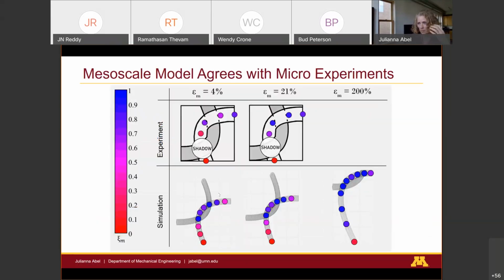We've also developed a mesoscale modeling approach. At the top, you see the experiments with very qualitative data. There's a lot of quantitative data in the paper, but you can see that as we go through, we have a larger martensitic phase fraction up at the top because it has a large bending radius. Then here at the inflection point at the base of the loop of this repeating structure, we have the lowest martensitic phase fraction, and so we get this distributed portion. What was interesting is this purple dot up here was unexpected to us, because we thought that, because of how the bending strains are applied, we'd be decreasing all the way throughout the structure. However, the compression within the structure between adjacent loops increased our stress at our contact points.